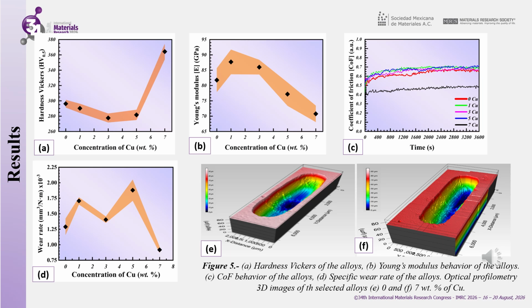The decline in modulus at elevated copper concentrations may be associated with alterations to the matrix, shifts in the proportion of crystalline phases, and increased microstructural heterogeneity of the beta-titanium phase. Consequently, while minor additions of copper appear to result in a modest increase in stiffness, higher concentrations seem to induce a decrease in the elastic modulus.